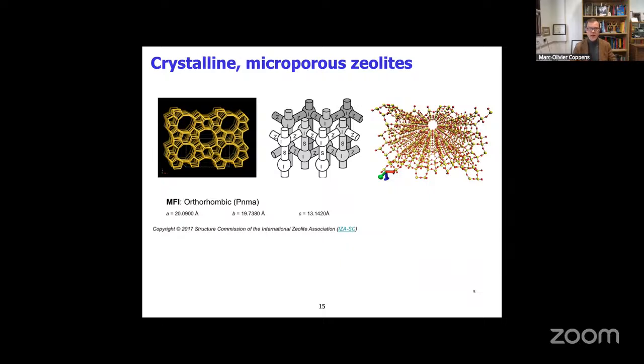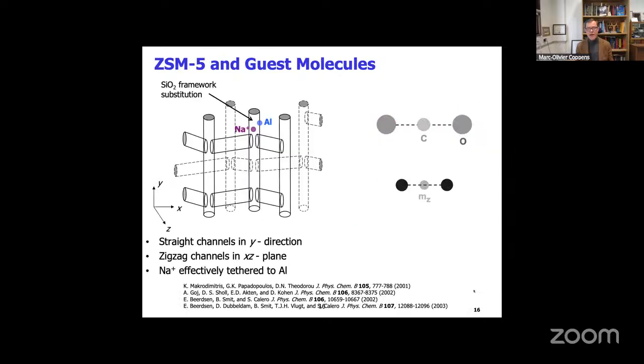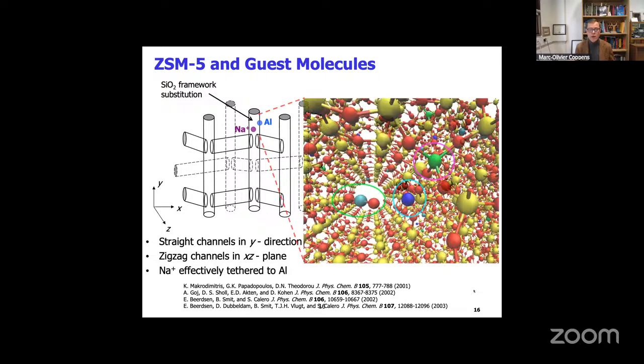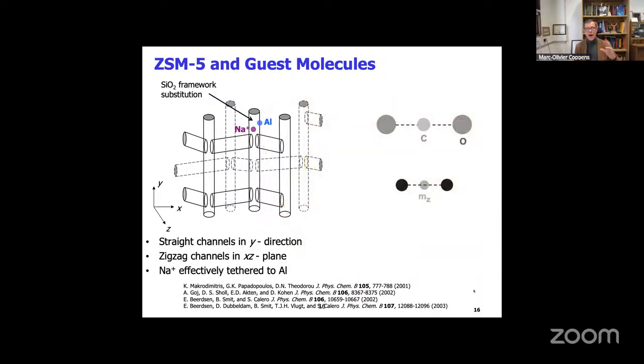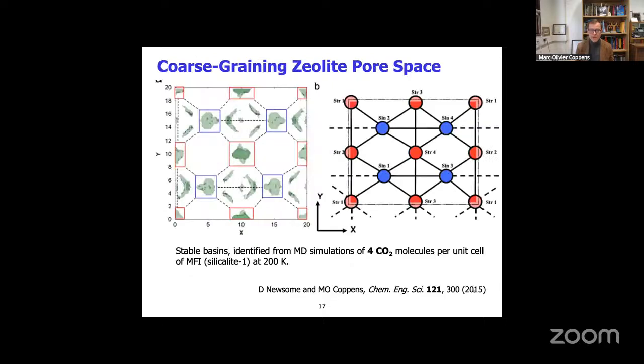So the atomistic models, for example, could be used for zeolites, although also there you can coarse grain the description of this pore space and identify, say here, for MFI, silicalite as the pure silicon form, or ZSM-5 with aluminum in it. You have intersections I, you have zigzag channels Z, and straight channels S, right? And then you can see how some of the sites in there are not silicon, they're aluminum, and they need to be counterbalanced, say, by a cation in this way. And then you can start looking at molecules like CO2 and involve their quadrupole moments, and nitrogen with its quadrupole, and how it interacts with this environment, and perform molecular simulations.